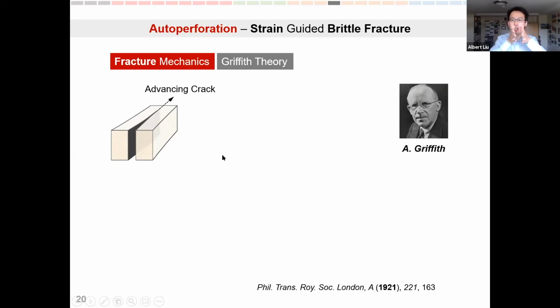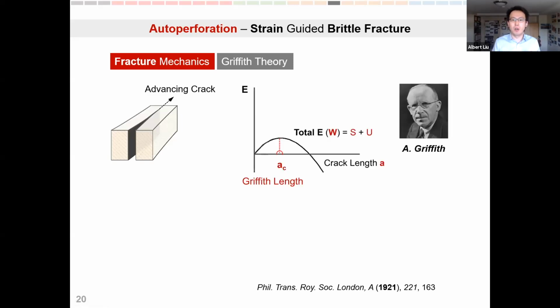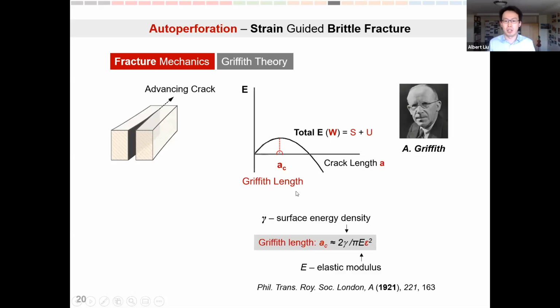So as we fracture a material and advance a crack within that given material, if you plot the overall system energy as a function of the crack length, it basically adopts this concave down shape. And you have the vertex of this energy landscape at the location of a critical length scale that is called the Griffith length. So if your seed crack within a given material is shorter than the Griffith length, you would notice that increasing the crack length is actually not advantageous because that increases overall system energy. On the other hand, if your crack is on the right-hand side of the Griffith length, the crack will propagate forever and the material will fracture. So Griffith length really controls the fracturability of a given material.